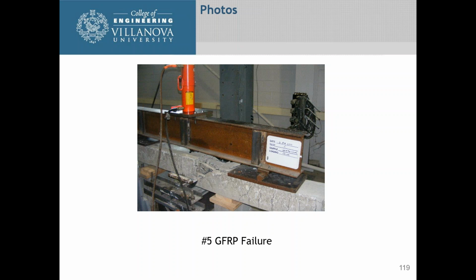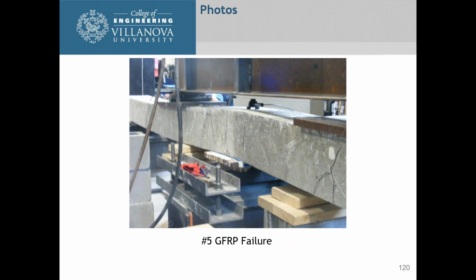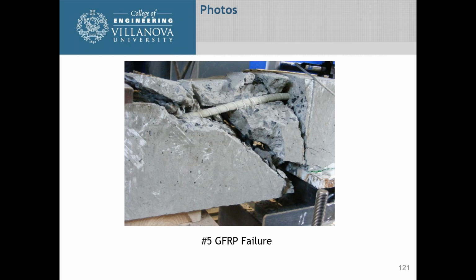And this is a number 5 GFRP bar that we got to fail. Here you can see an idea of how flexible these samples were and how much deflection we were getting. This is with the number 5 GFRP bar. And again, this is a failure that we got on one of the samples, where it's failing from that plate to that plate, and the GFRP bar held together very well. We had a heck of a time just cutting these apart.